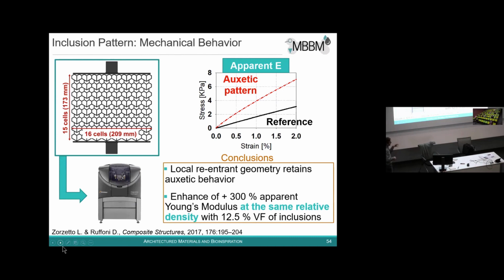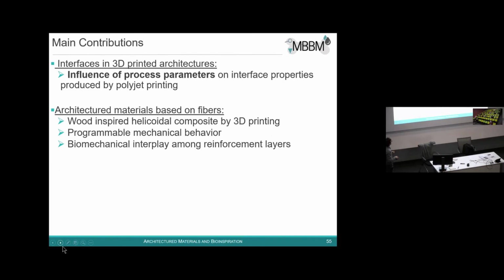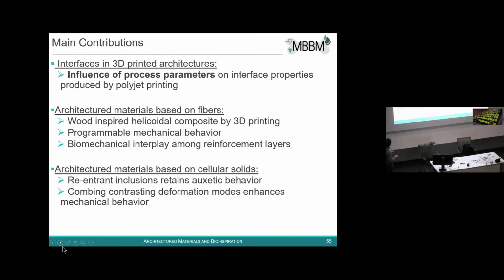So what I find nice is that we don't put more material. We are not changing the anisotropy. We are not orienting this differently. The anisotropy, or the isotropy, let's say, stays the same. The relative density stays the same, but because of this contrast in the deformation mode, we increase the stiffness up to 300%. And yes, I think this is now the conclusion.